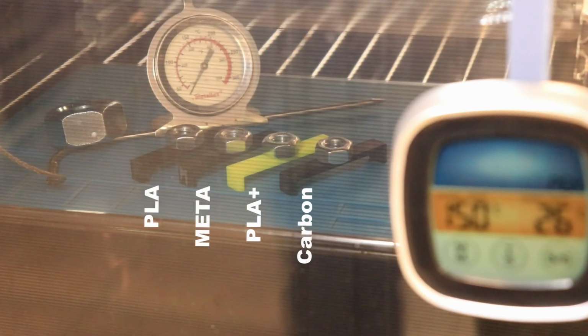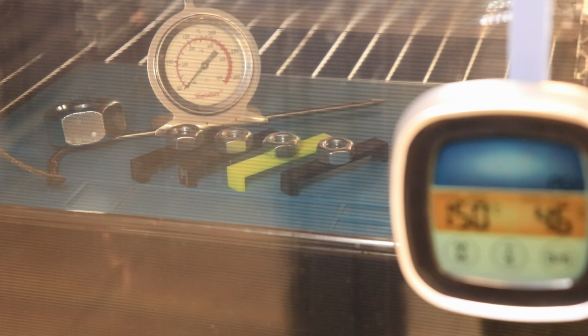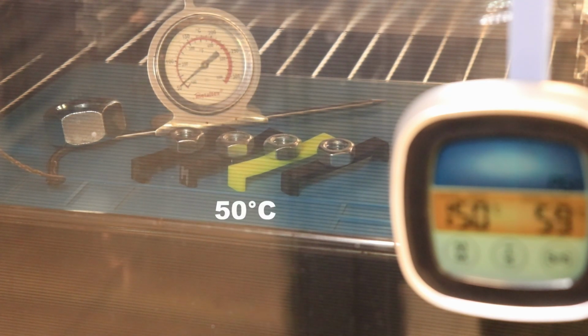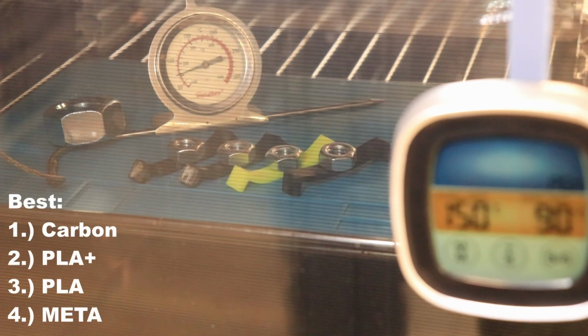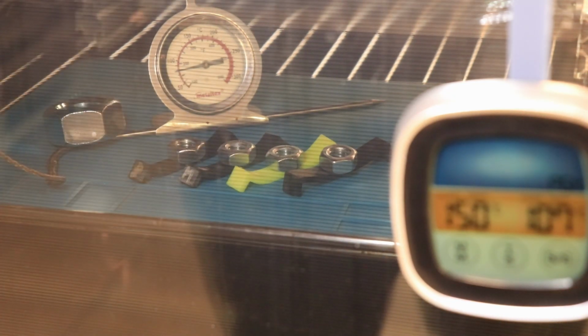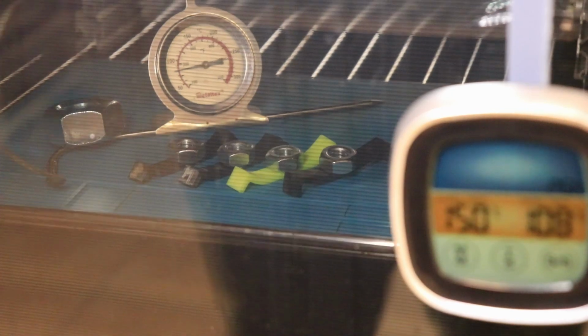And this is the time lapse of approximately 5 minutes. Don't be confused, the backup thermometer has a small delay, more accurate is the cooking thermometer. And as expected, all 4 PLA filaments started with deformation on 50 degrees Celsius. Only I noticed that the further deformations had a different speed. I will stop the experiment now on 100 degrees Celsius because I want to see the condition of the carbon filament.